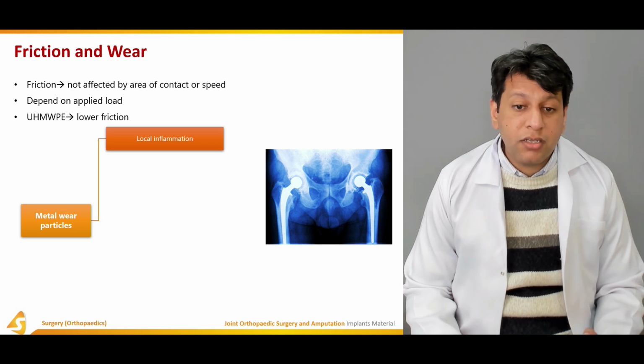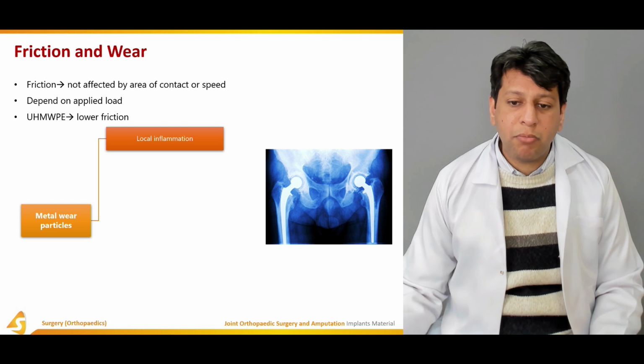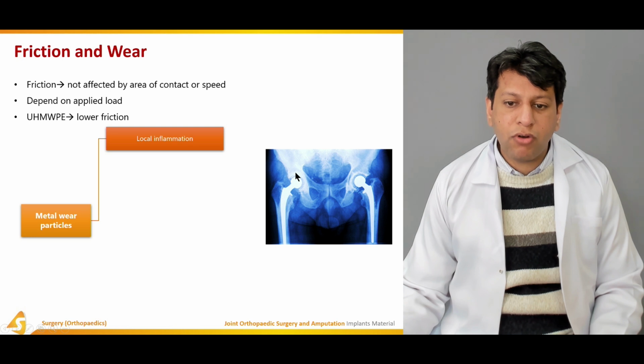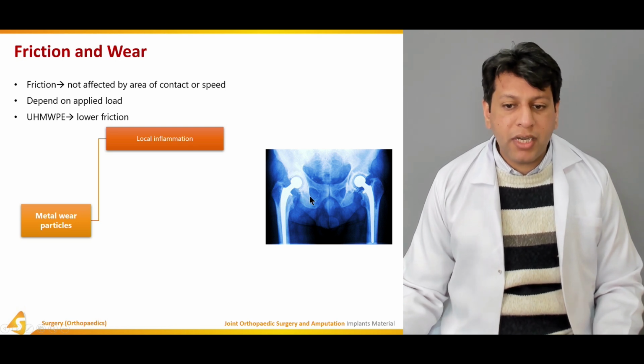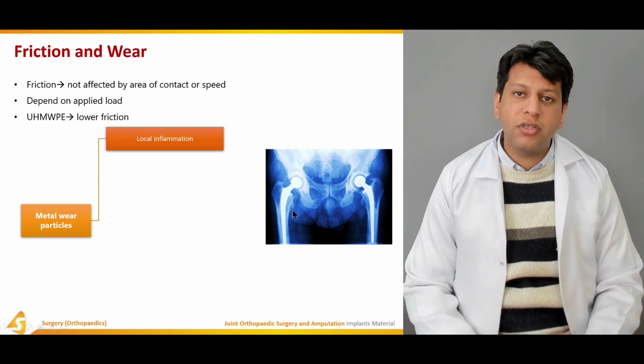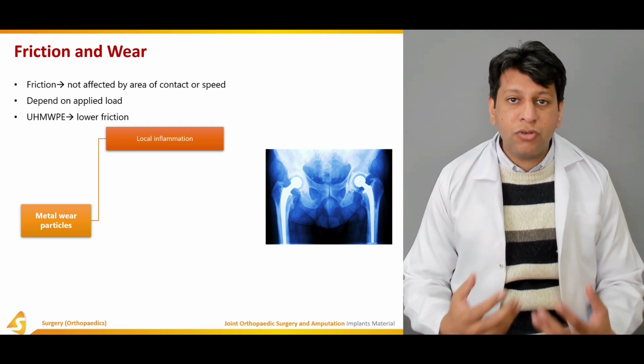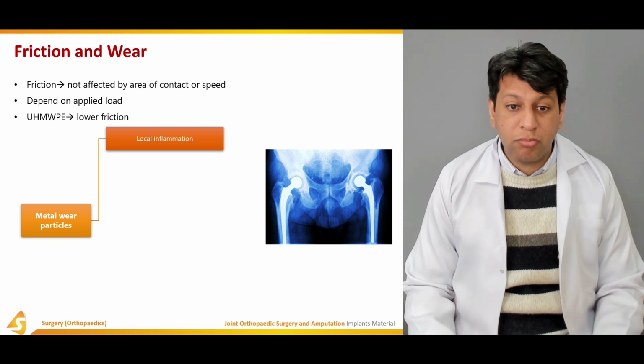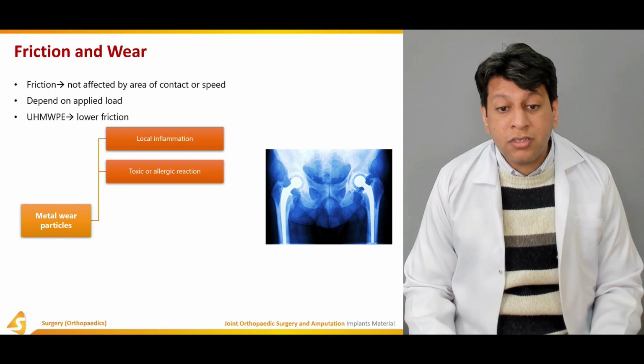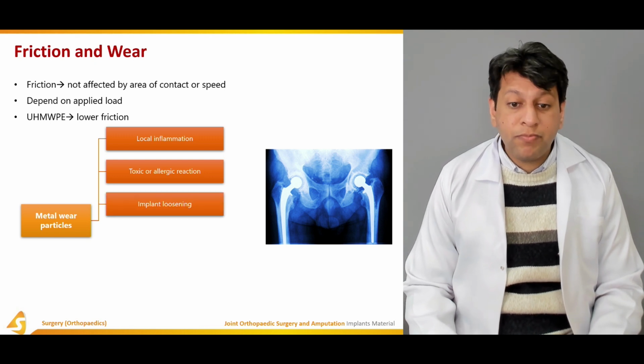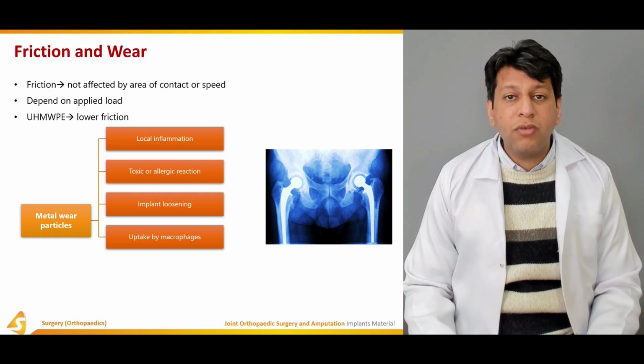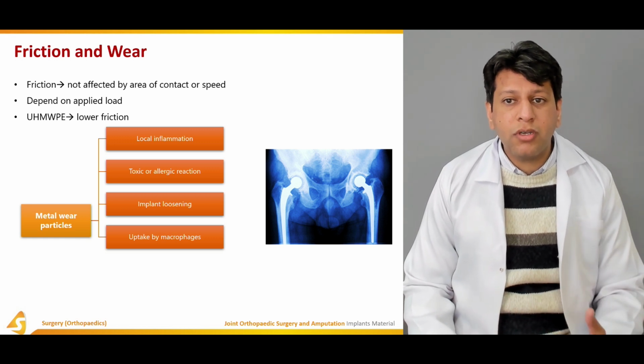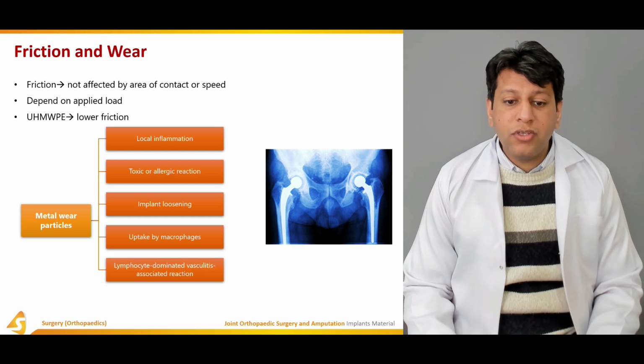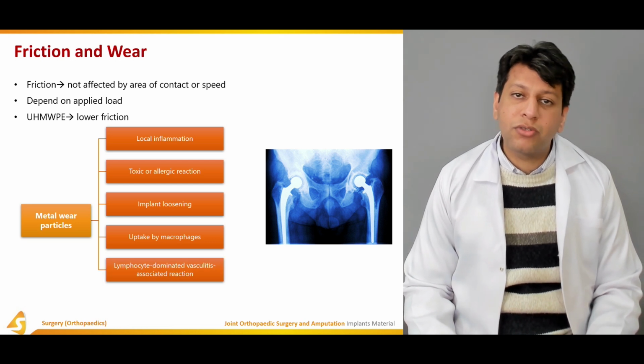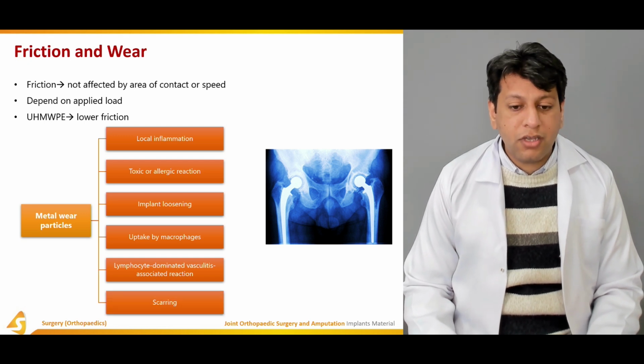Metal wear particles could be problematic. For example, if you're seeing this over here, this is using a femoral component over all poly rather than a metal component. But when a metal on metal component is used, it can result in abrasion, and usually metal or metal ions can be discharged into the blood. This can not only produce local inflammation, it can produce a toxic or allergic reaction and implant loosening as well. And usually once this is taken up by macrophages, they produce a foreign body reaction to it as well, eventually leading to a lymphocyte dominated vasculitis associated reaction and or scarring.